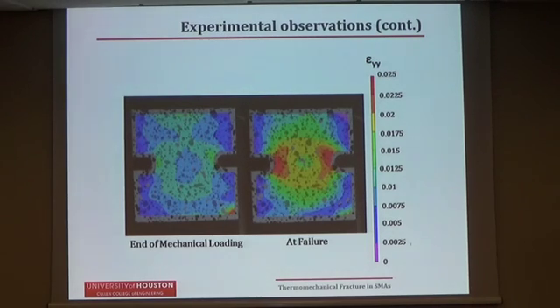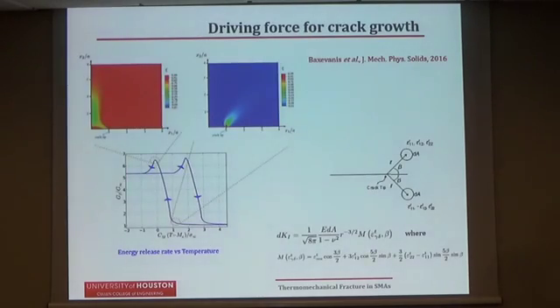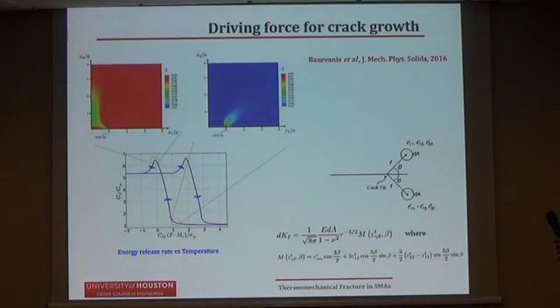They should redistribute the stresses, and in fact this is the case both from numerical simulations and from analytical calculations that we have done using the weight function theory. We have found out that as long as phase transformation happens in a fan in front of the crack tip, it tends to open up the crack. Whenever phase transformation happens behind the crack tip, in the wake of the crack, it induces some compressive stresses and it tends to close the crack.